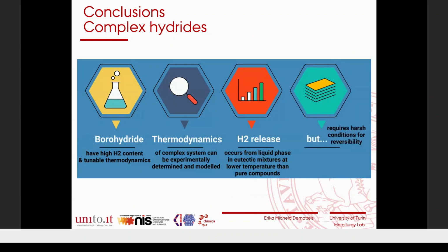So as a preliminary conclusion for complex hydride, we were able to see that borohydrides have really high hydrogen contents and tunable thermodynamics. The thermodynamics of the complex system, binary and up to ternary, can be experimentally investigated and also modeled. And hydrogen release, that I didn't show in this short presentation, but I can say that occurs from liquid phase in eutectic mixture at lower temperature than pure compounds. So this was an enhancement of hydrogen release in this kind of compound. However, still we require harsh conditions for reversibility in complex hydride.